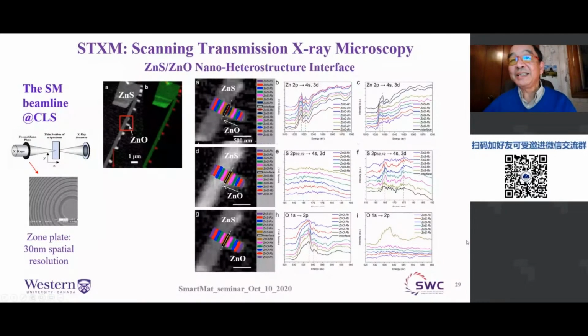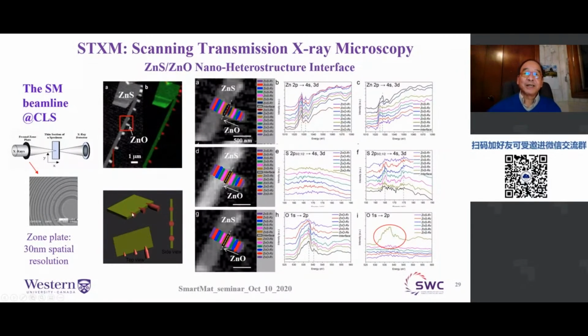The interesting thing is that each of these slabs gives us a spectrum. Each spectrum corresponds to what we call the region of interest in this step, which is about 200 to 300 nanometers, so we can do nanospectroscopy on the region using this technique. Making a long story short, we do all the spectroscopy and come up with a conclusion. You can see that once we go into the oxygen region, the oxygen absorption pops up, right? So our conclusion is that in this particular construction, the zinc oxide is actually embedded into zinc sulfide.